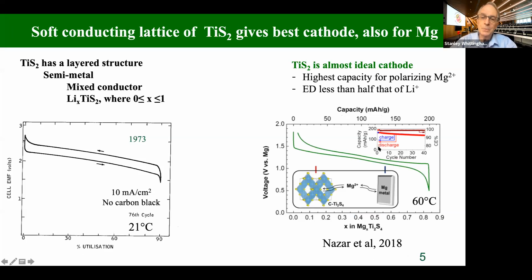So if we look at today's work, Linda Nazar and her team used titanium disulfide as the cathode for a magnesium battery. Because it's a metallic conductor, the electrostatic interactions are shielded, so the magnesium ions can diffuse fairly readily through the lattice. And you can see the cycling curve here. Very little polarization. There's 40 cycles here, essentially 100% Coulombic efficiency, and very little fall off in energy as it cycles. But you'll notice the discharge potential now of magnesium is about 1 volt less than that of lithium. So even though it cycles well, it is not really a realistic battery system long term.